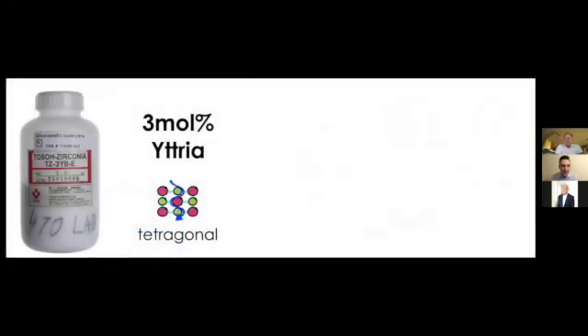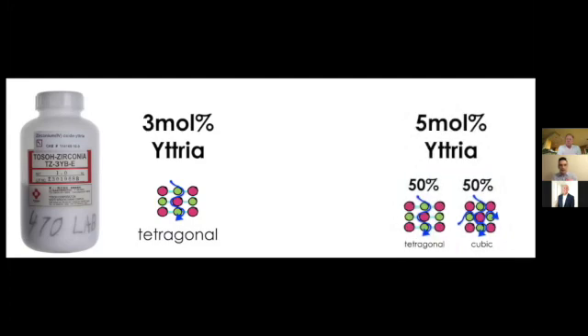And so how did they get that cubic zirconia, translucent zirconia into the newer types of zirconia? They do it with this little molecule, yttria. When you add yttria to zirconia at 3 mol%, you get something like the Bruxer type materials, the things that are all tetragonal and very opaque. In order to get some of that cubic in there, you've got to throw in 5 mol% yttria. Actually, if you throw in 8 mol% yttria, you'll get 100% cubic zirconia. 5 mol% yttria, you'll get 50% cubic zirconia.